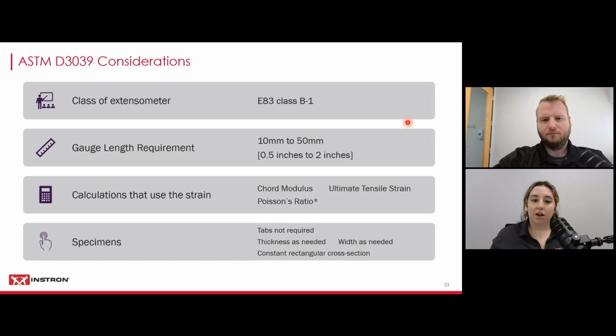So, considerations for ASTM D3039. For the class of extensometer, it requires E83 class B1 at least. And if you have a good memory, you remember that clip-ons, we said that they're guaranteed to meet ASTM class B2. When you're getting your clip-ons calibrated, you do have a better chance of reaching class B1 if you have a larger gauge length and low travel.